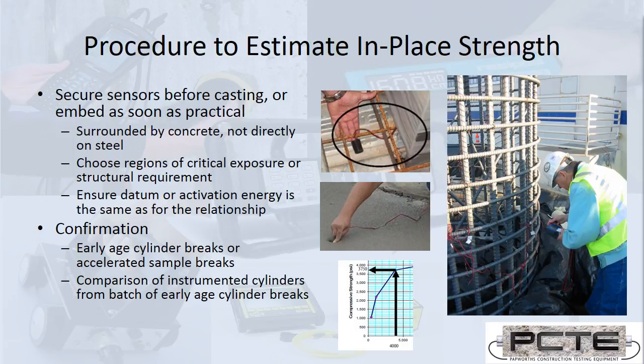Then, once we've got our curve built, we need to take measurements out on site. The sensors need to be cast into the concrete or placed into the concrete immediately after the concrete is poured. They need to be away from things that might take heat away from them. So if you have a large amount of steel reinforcing, the sensor needs to be a little proud of that, so it's not allowed to cool or heat more quickly by the change in heat of that steel. And there's a datum or activation energy parameter used by each of the maturity indexes, and the sensor needs to have it entered correctly at the beginning. Otherwise the data will need to be adjusted afterwards.